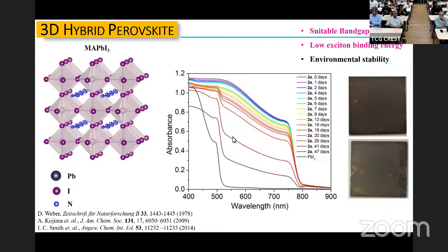What is being shown over here, again, is a UV absorption curve. When you make the material, you have a band gap near 1.5 electron volt. 800 nanometer, I told you, is 1.5 electron volt. As time passes, you can see that it gets shifted, and this is PbI2. The system just degrades into PbI2 in presence of moisture. And moisture is inevitable. I don't have to convince you in Calcutta about moisture. So that really destroys the device very, very quickly. And you need to think about this stability. And that is what brings us to the 2D.